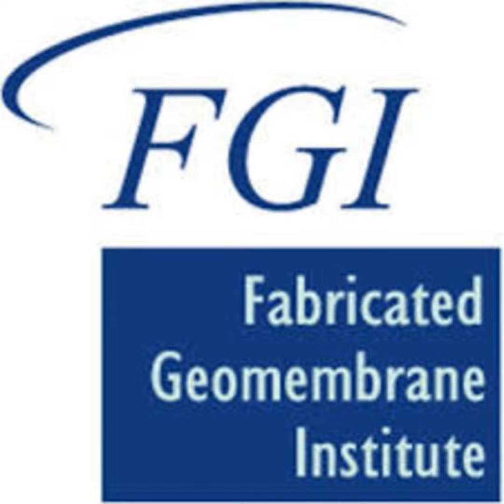Yeah, so this is, again, building off some of our previous discussion, and unfortunately, as we've talked about, Tim, there's not a single stress level that you could identify, because the normal stress level at which we see that transition from the critical interface being, say, between the GCL and the geomembrane, or the GCL and the neighboring soil, or the geomembrane and the neighboring soil, to eventually being internal in the GCL is going to be different as a function of the material properties of the GCL and the geomembrane.